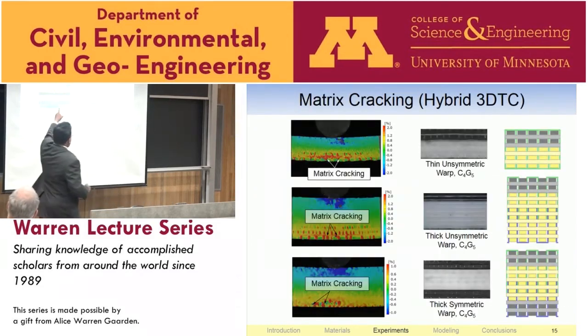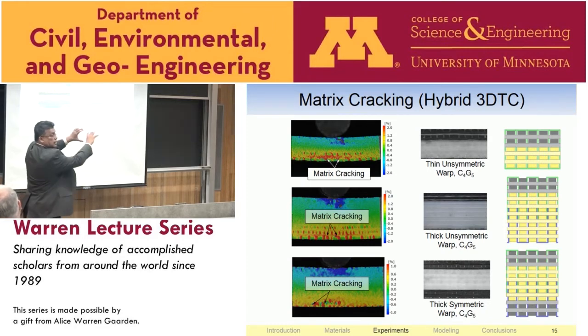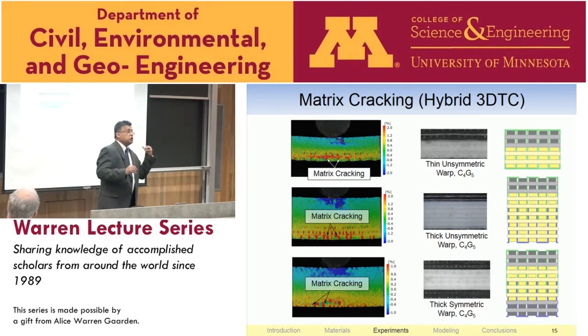So here are those DIC pictures that we can analyze. You can see that the micro cracking in the matrix sets up at the bottom, and then finally, when it completely collapses at the top, you get those kink bands, and they progress while it's propagating. Now, this is a huge challenge for modeling, right? So all glory to one of my students that did this work, Dianyun Zhang. She's now a professor at University of Connecticut in mechanical engineering.